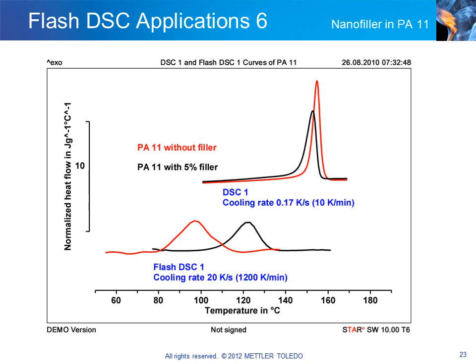In the conventional DSC, the unfilled polyamide crystallizes at higher temperatures than the filled polyamide at the low cooling rates used. The opposite effect is observed at the high cooling rates of the Flash DSC-1. The filler then functions as a nucleating agent.